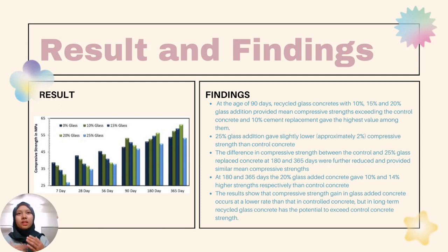The differences in compressive strength between the control and 25% glass replaced concrete at 180 and 365 days were further reduced and provided similar mean compressive strengths. At 180 and 365 days, the 20% glass added concrete gave 10% and 14% higher strengths respectively than the control concrete. So the results show the compressive strength gain in glass added concrete occurs at a lower rate than that in control concrete. But in the long term, recycled glass concrete has the potential to exceed the control concrete.